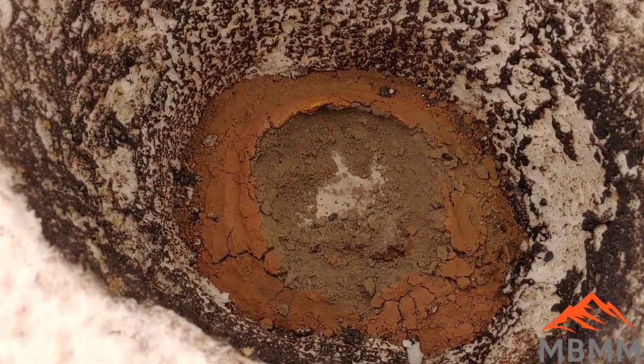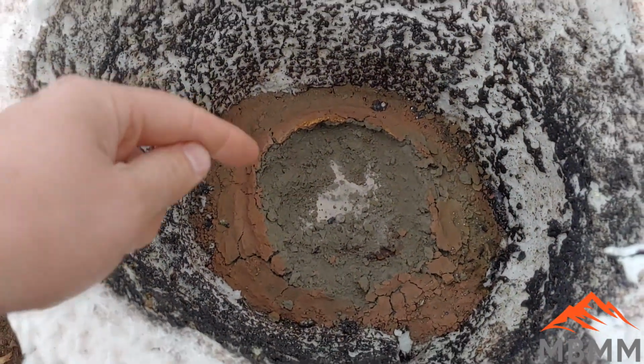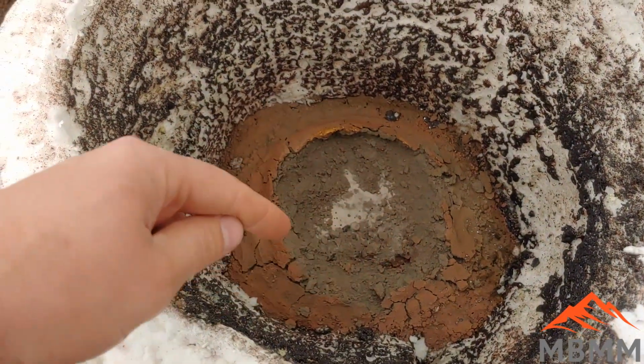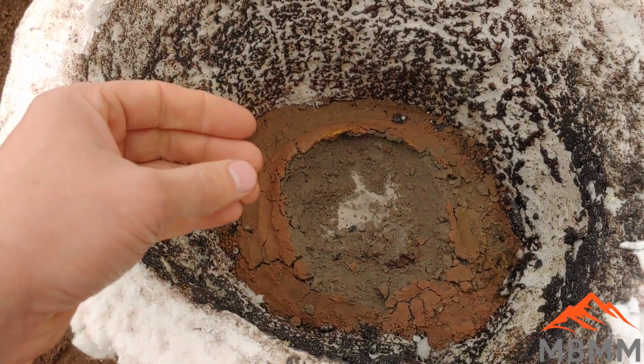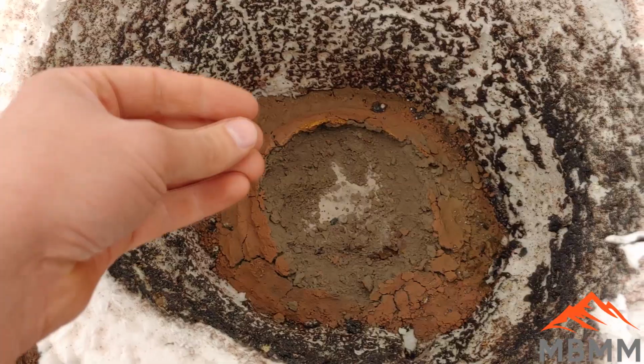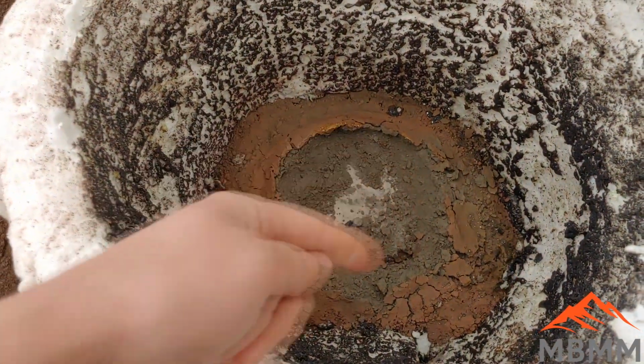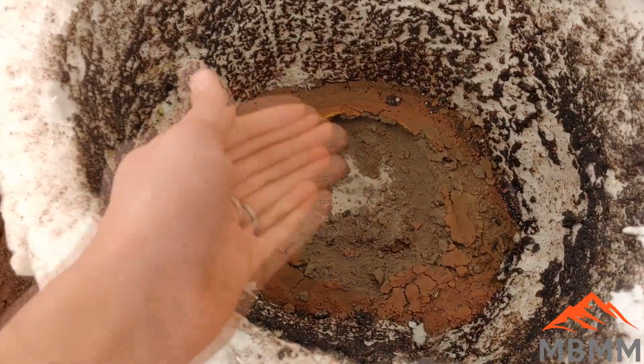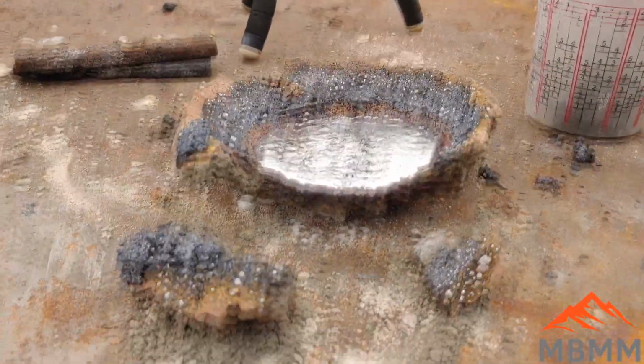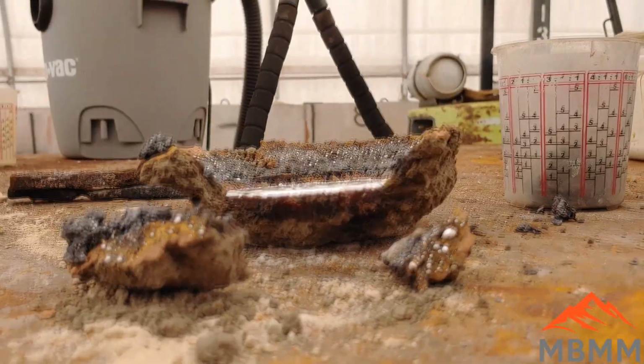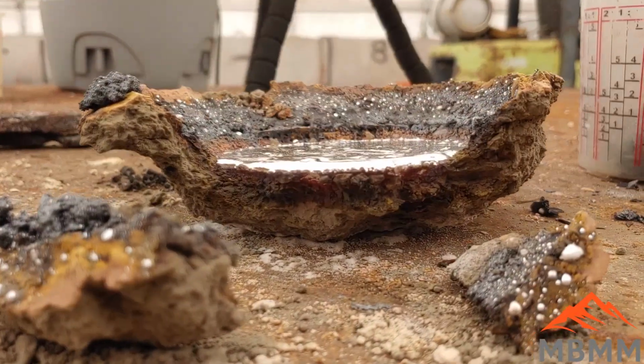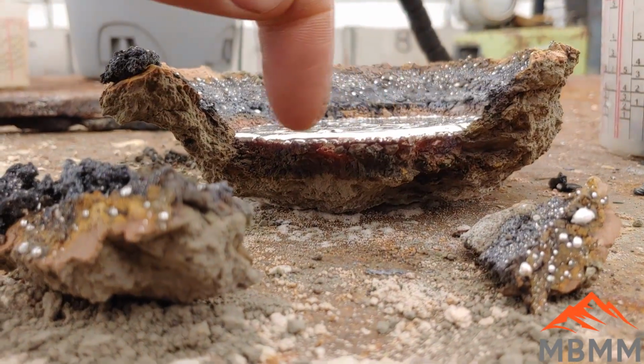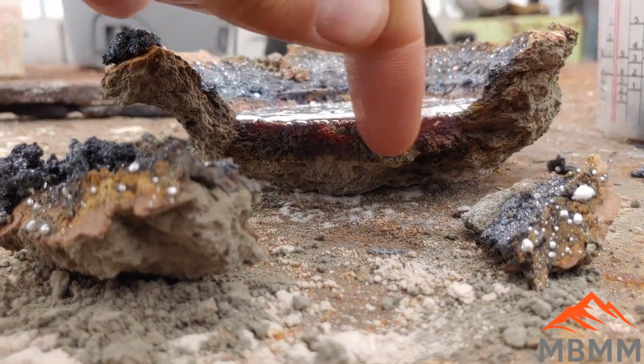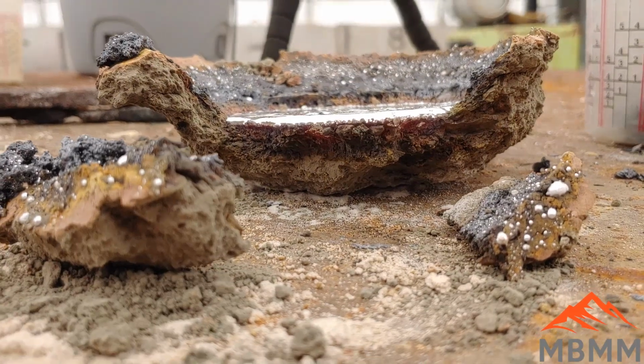So I've pulled our silver out of there, and the nice part when doing this is all the lead oxide, the litharge, actually bonds the cement together. So when you go to pull it out, you pull out all the contaminated cement, and all this is still just Portland cement. I can actually reuse that. I can pack a little more in there and do another cupel. Over here, you can see what came out, and here's a cross section of what that looks like, and that silver wafer sitting right here on top, and then the lead oxide has permeated into the Portland cement down there, maybe an inch.